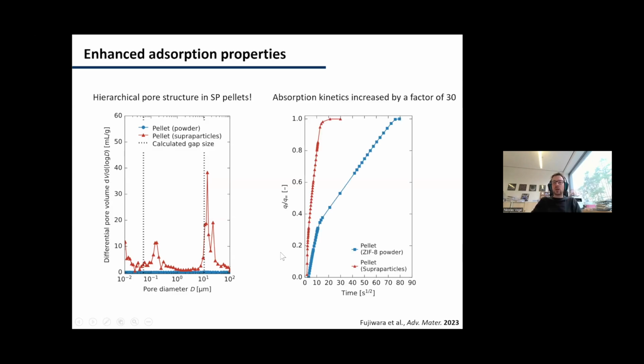And when we now look at the kinetics of the adsorption, what you see here in blue is a normal powder of such a metal organic framework. And you see it takes quite a long time until we saturate the pores and adsorb all the gas. And in contrast, a pellet made from superparticles, because now this is much more porous and has these large transport pores, can be charged really, really quickly, by a factor of approximately 30 difference.